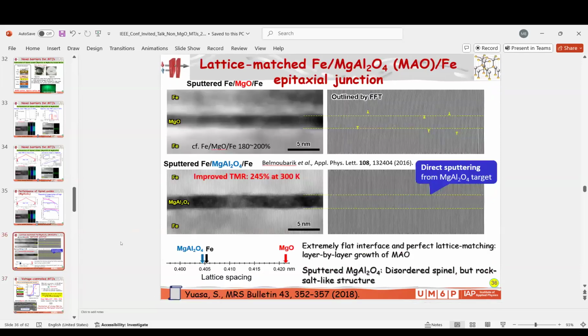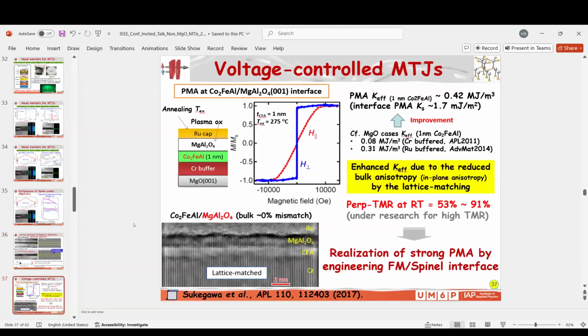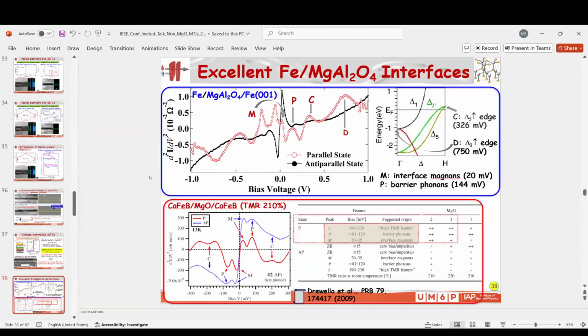Here's the illustration of the lattice spacing. If you enlarge the scale, MgO is here, iron is here, and the spinel is here. As a consequence, in a study done by Dr. Sukegawa at NIMS, we could increase the PMA performance. I will go through.